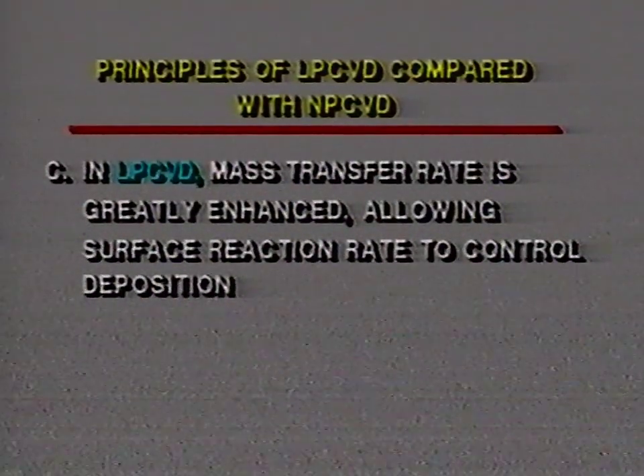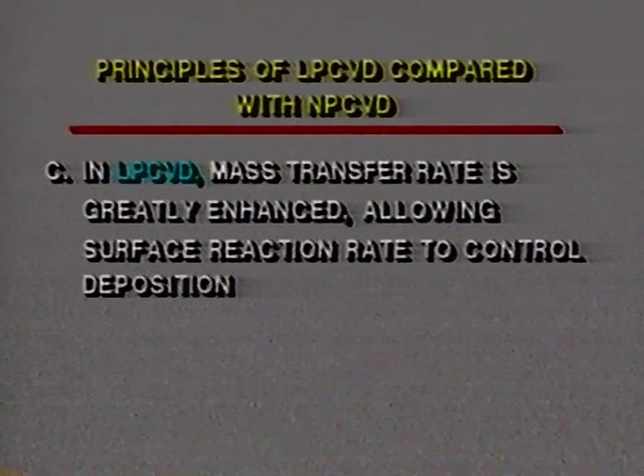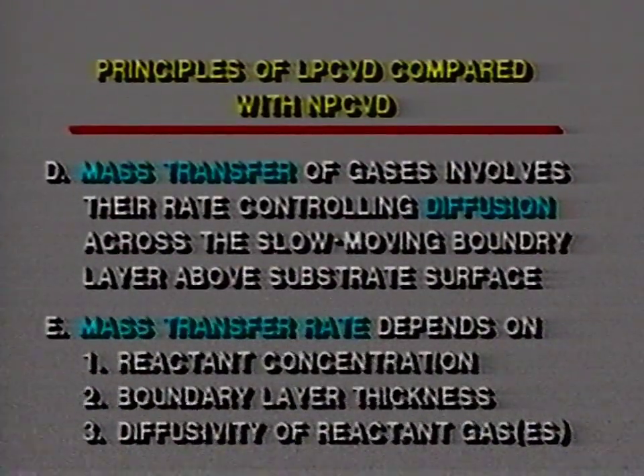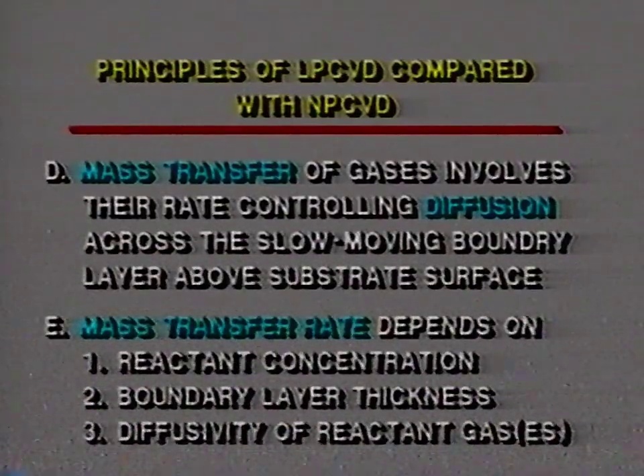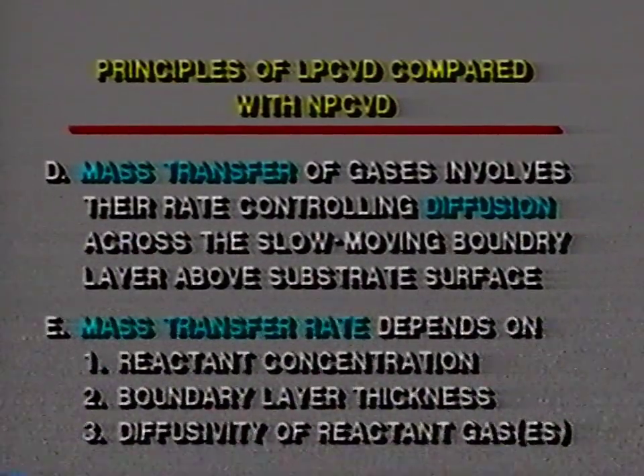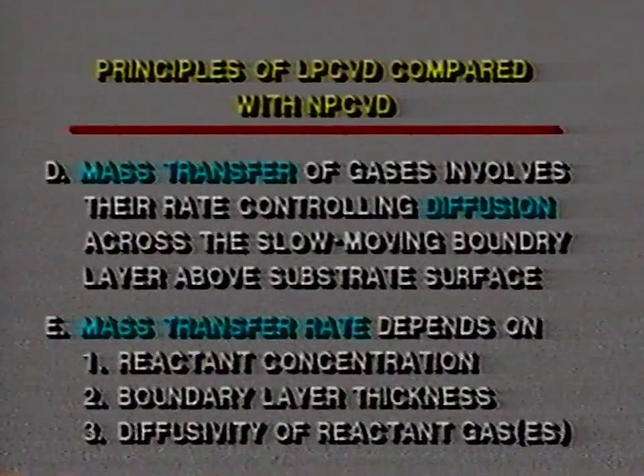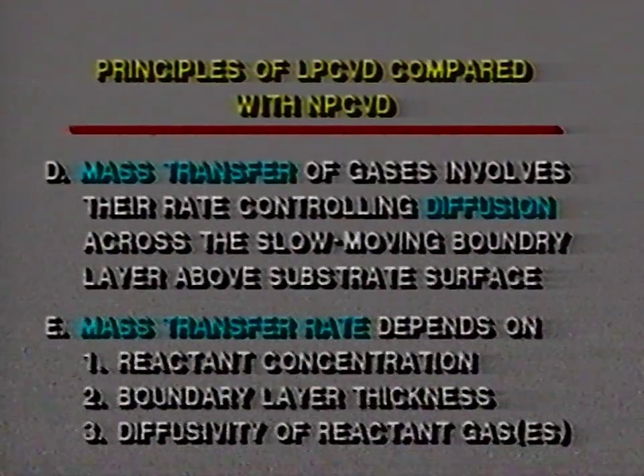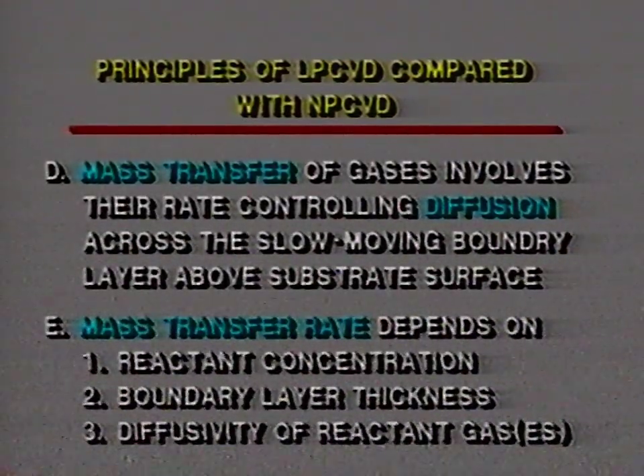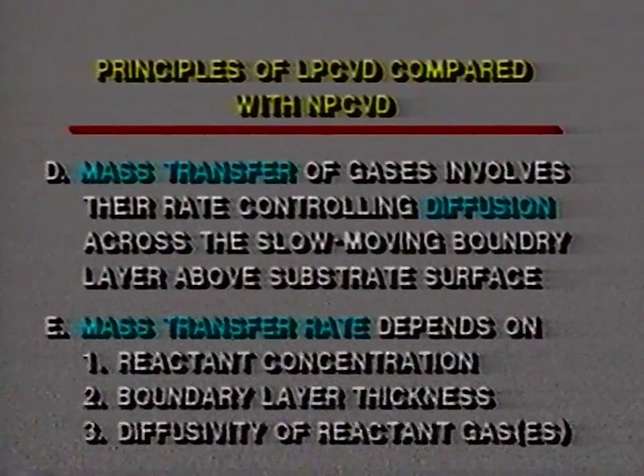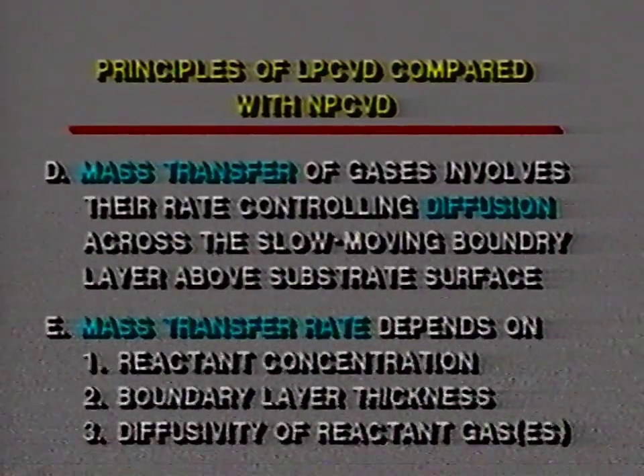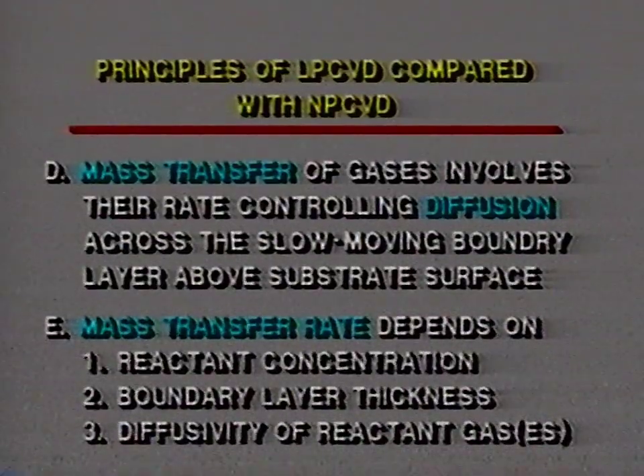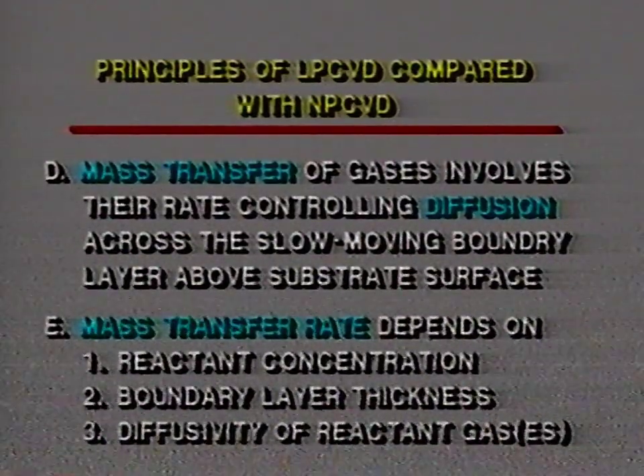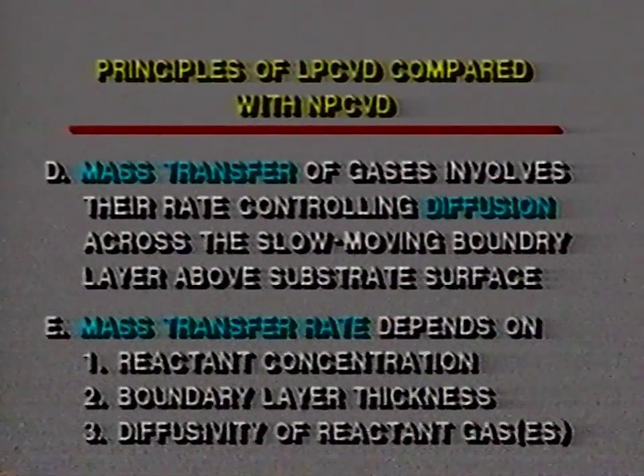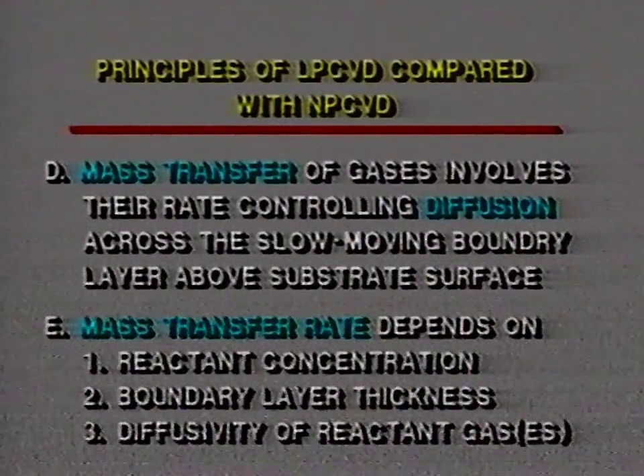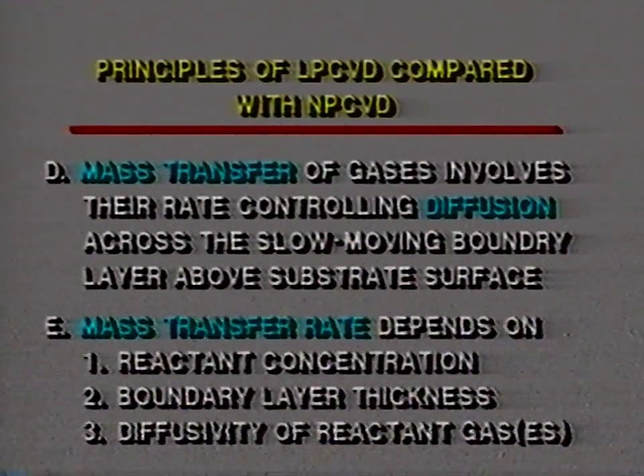Now let's examine this in a little more detail under D. And here we show that the mass transfer of gases involves rate controlling diffusion across a slow moving boundary layer, which is always present above the substrate itself. Now this boundary layer is the limiting factor here, and that is a very important aspect, the transfer of the gases through this stagnant layer, the boundary layer above the surface.